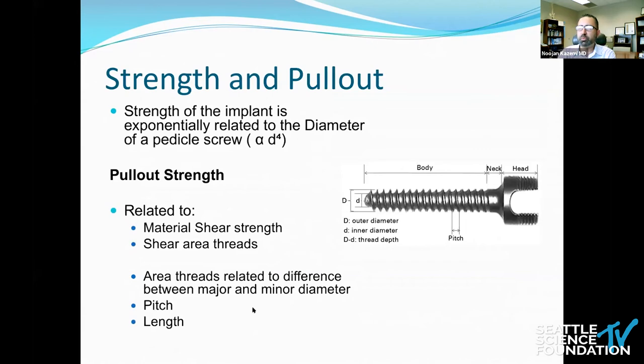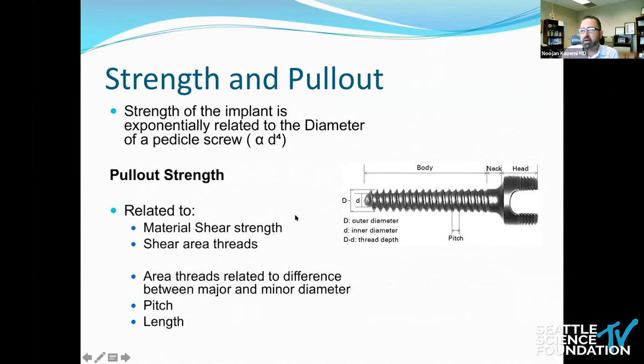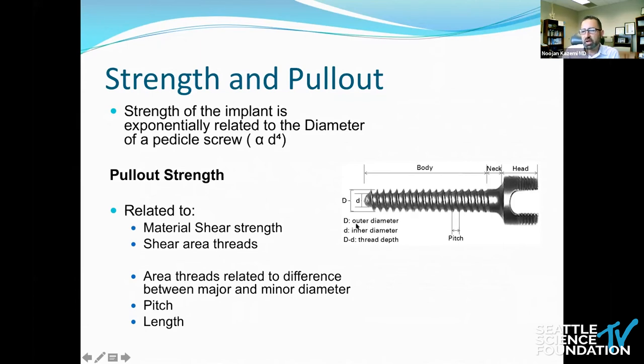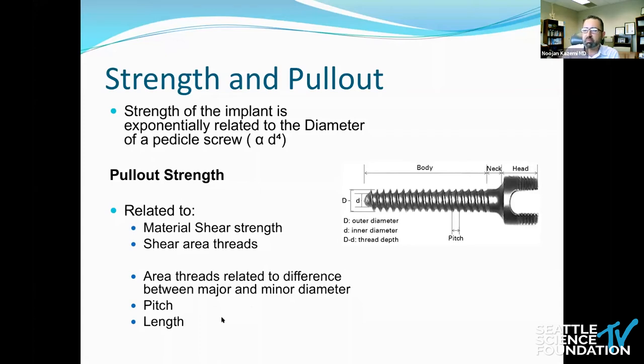The strength of the screw implant is related exponentially to the diameter — particularly the inner diameter — to the power of four. So the greater the diameter, the much stronger the tensile strength. The pullout strength — the resistive ability of the screw to be pulled from the bone interface — is not just related to the shear strength of the metal-bone interface, but also the area across which osseointegration is applied. That's really the difference between the major and minor diameter. The greater the difference, the greater the ability for osseointegration and hence pullout resistance. It's also related to thread frequency, pitch, and the length of the screw.